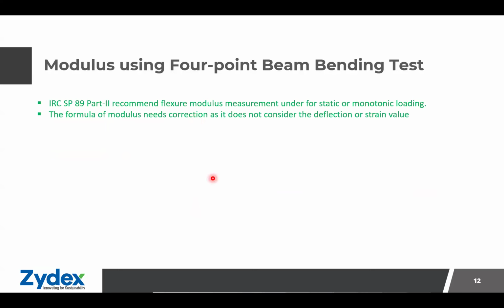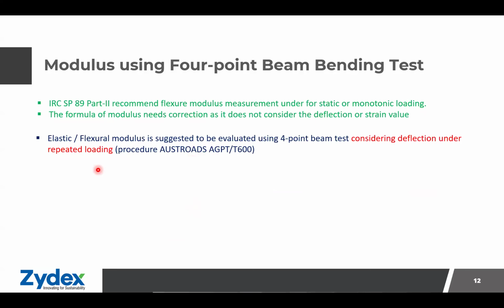Also, the formula for modulus needs correction as it does not consider the deflection or strain value while calculating the modulus. Therefore, it is important to measure the flexure modulus using a 4-point beam test, considering the deflection as well as under repeated loading conditions. This is important because the flexure fatigue models are developed considering the modulus under repeated loading. The modulus that we get from the monotonic loading as well as under repeated loading may not be the same.